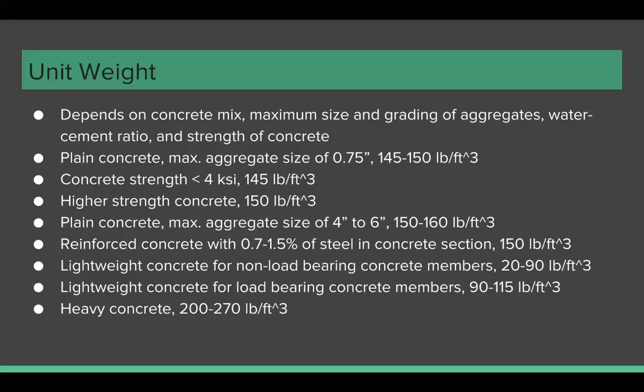For lightweight concrete that's used for fireproofing, masonry, or insulation purposes, the weight ranges between 20 to 90 pounds per cubic foot. If the concrete is to be used in load-bearing concrete members, the weight is somewhere between 90 and 115 pounds per cubic foot.